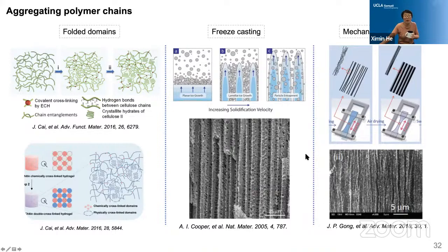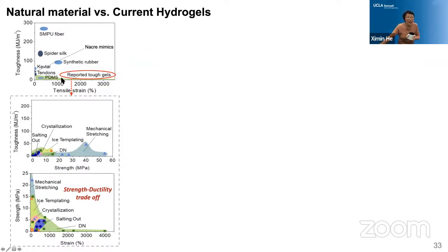So all these very effectively enhance the toughness of hydrogel. They are basically located in this green region. But if you compare this reported tough gel with other natural materials or even some elastomers, they are still at a lower end. Also, if you further zoom in, you can see a lot of these strategies can either enhance the strength or the ductility, or stretchability. So overall, you still prefer to have a high toughness, which arises from both enhanced strength and ductility without compromising one or the other.